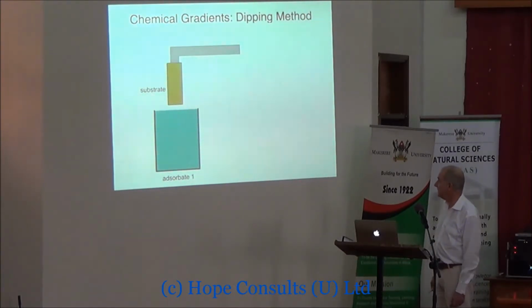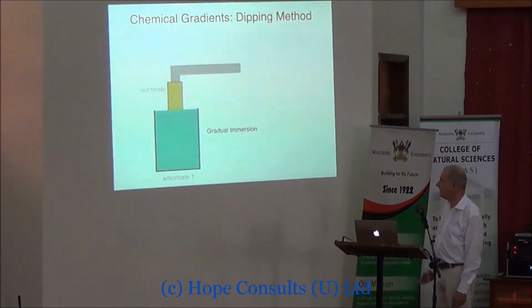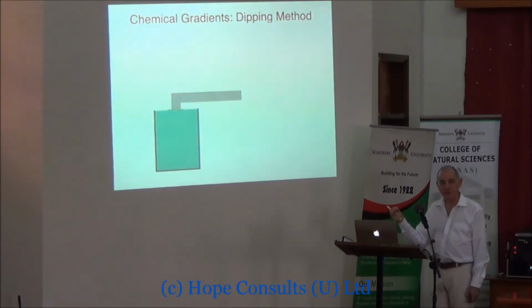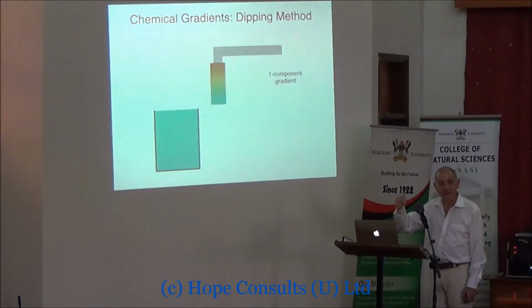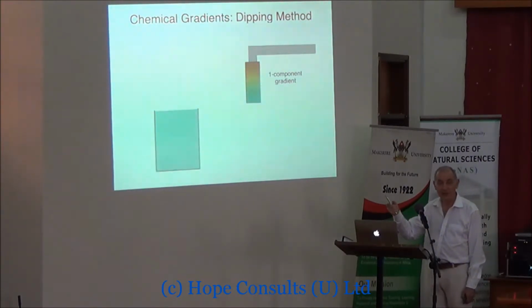So you have a clean gold surface. You can even buy clean gold surfaces that you then strip off a template, like I described with the ultra-flat surfaces. And then you take your clean surface and you dip it into a solution of one of your thiols. And you dip it in slowly. And if you dip it in slowly, then because the adsorption has a certain kinetics, the leading edge will have a higher concentration than the trailing edge.